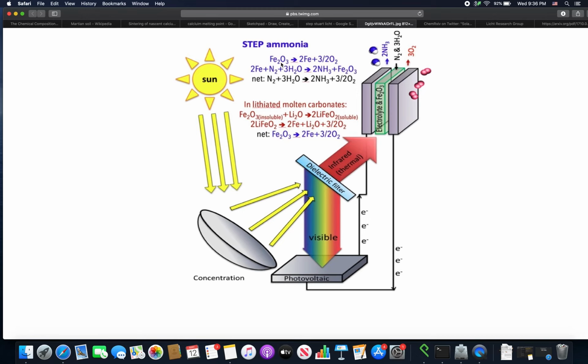Another thing that makes this process so efficient is, if you're looking at the one that we would use for space, we would use lithium carbonate. And lithium carbonate, or the other carbonates, have CO3. It's Li2CO3 is lithium carbonate. So that is 2 lithium atoms, small, 1 carbon atom, and 3 oxygen atoms. And CO3 is the negative part. Or you can have sodium carbonate, which is 2 sodiums and the rest is the same, and so on, and mixtures.